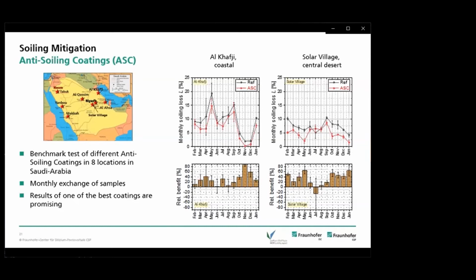And the relative benefits varied between 0 and up to 90%, depending on the months. And also in some months we had more soiling on our coatings, which could also happen. But anyhow, on the average, we had more than 30% soiling reduction, which was a really nice outcome.